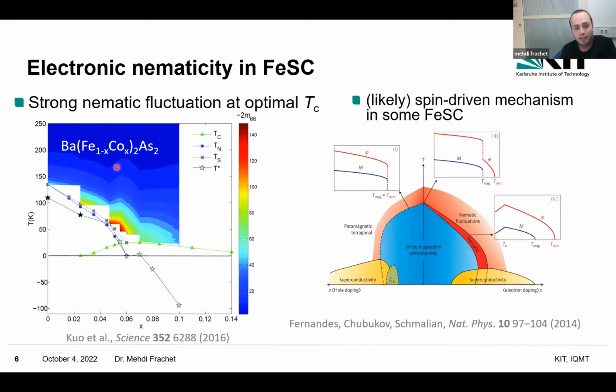So electronic nematicity is, I would say, an exotic electronic state of matter, which is interesting in itself. But what makes it even more interesting, at least to me, is its interplay with superconductivity in some compounds. An example is cobalt-doped barium iron arsenide, again a paper from the Ian Fisher group. The color code is the strength of the nematic fluctuations in this B2g channel. Close to the optimal condition for superconductivity, there are strong nematic fluctuations, which suggests that such fluctuations could enhance the superconducting pairing.